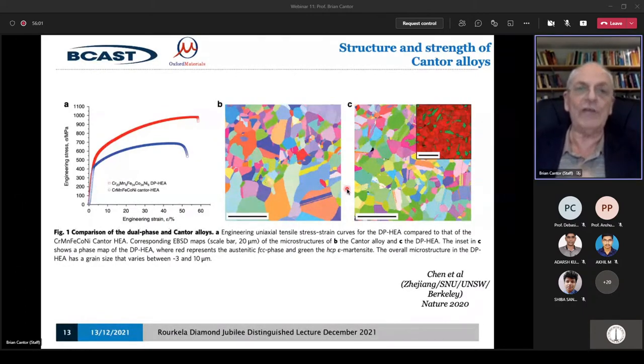And what they discovered, we knew they would have interesting and unusual and exciting properties, but they discovered this particular one. So this is a stress strain curve. You put stress onto the material, and this is how much it changes shape. Initially, it changes shape elastically. It requires a lot of force to change it elastically because you're pulling the atoms apart a little bit, and their interaction energies of attraction are very strong. So you don't get much movement. And that's elastic deformation. And then with metals, they start to deform plastically. In other words, they start to deform and set with a plastic change of shape. And that's in this region here.